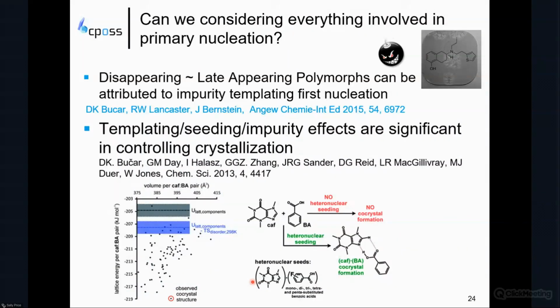But I think this gives you some idea of the problems of considering everything involved in primary nucleation. Remembering that the big problem in polymorphism for the pharmaceutical companies is where you have a very late appearing polymorph that, once you have the seed crystals of that polymorph and it has been crystallized the first time, causes you to lose control of your production process. And a lot of these late appearing polymorphs have been attributed to some sort of impurity templating the first nucleation.